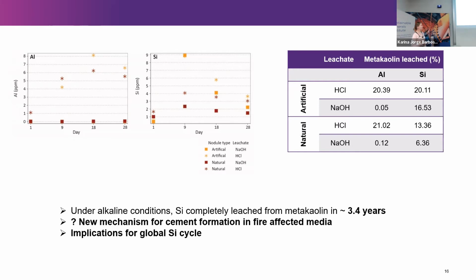So potentially what we could be having is, as I mentioned earlier, following a wildfire, we have pervasive alkaline conditions for a period of time. What if we were incongruently leaching the silica from these samples, leaving behind an aluminous cement? This is a big question. My leaching experiment only lasted for 1 month, so not enough time to fully cement anything. I think a long-term leaching experiment would be quite interesting.